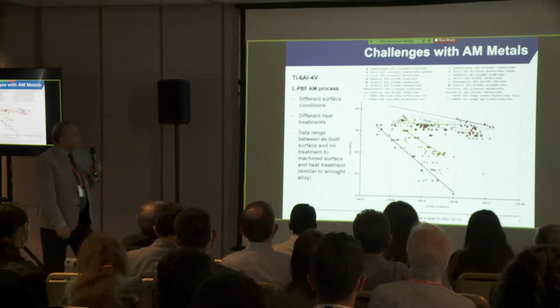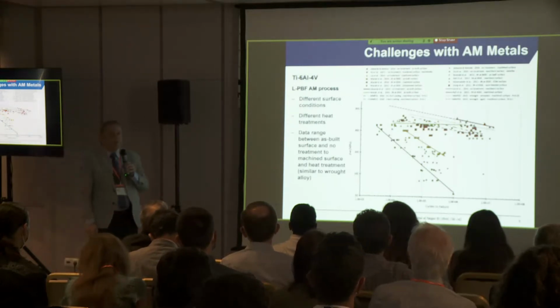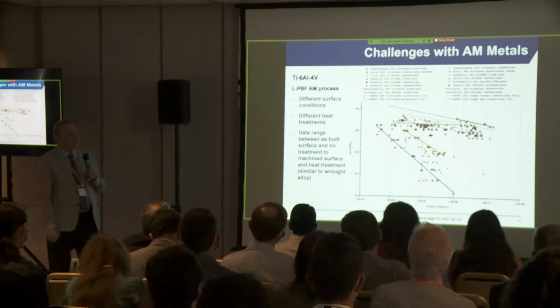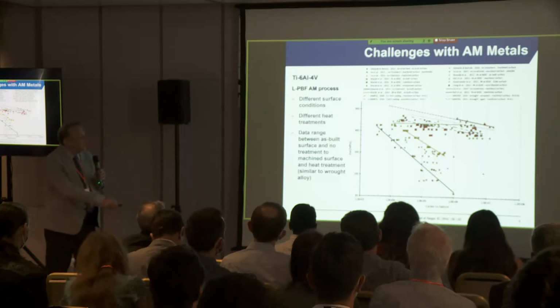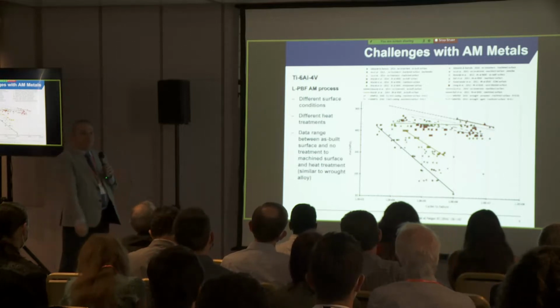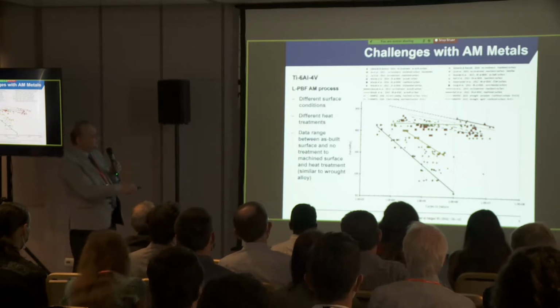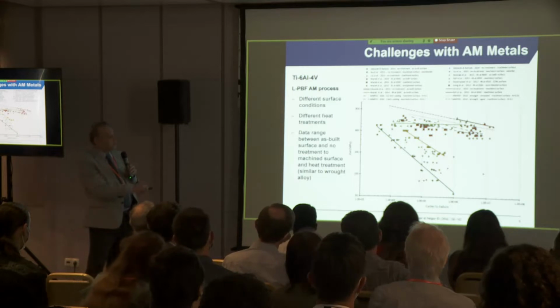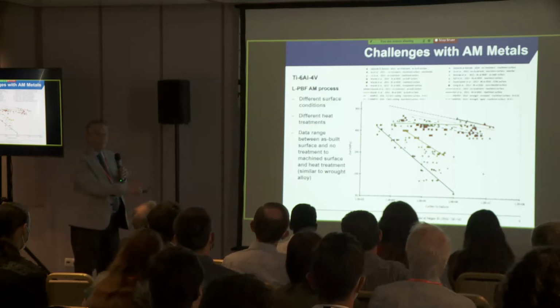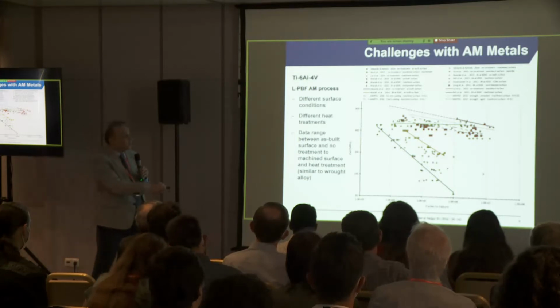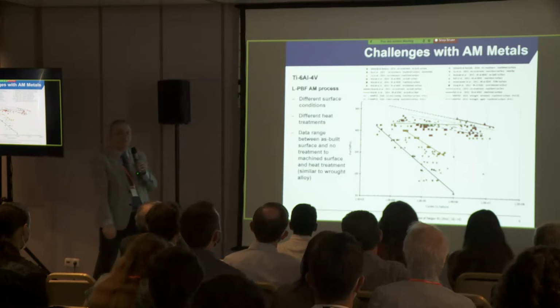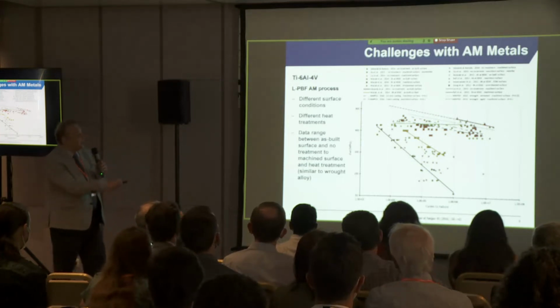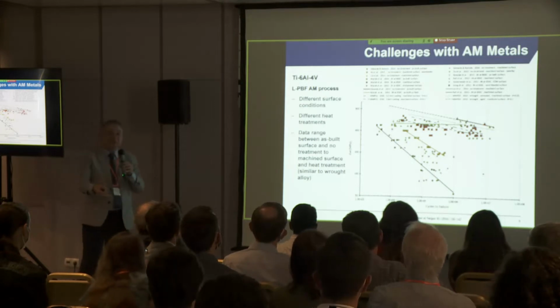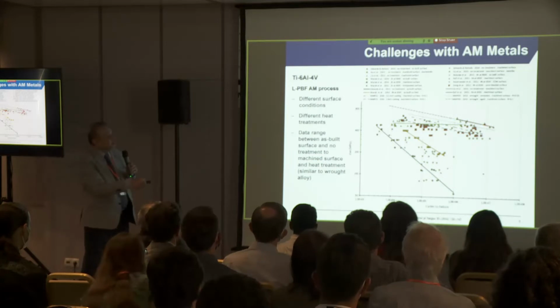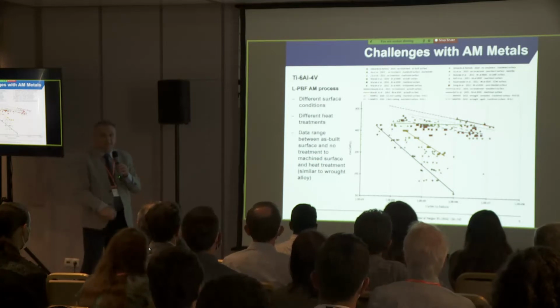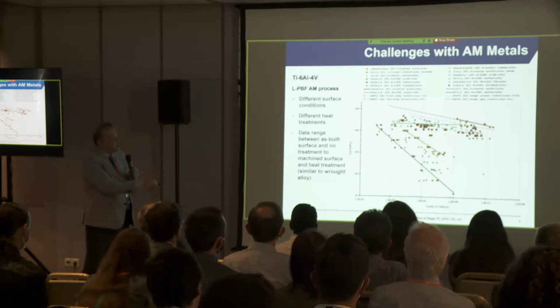Okay, now, because of these variations I talked about, if you look at fatigue performance of just titanium Ti-64, just one single alloy, this is the kind of variation you see in SN diagram, which is tremendous variation of data. So the data could be as bad as what it is here for a process with rough surface finish or as built surface finish and no treatment, all the way up to a process which is machined and not only machined, post-process with HIP, for example, and you can see then the behavior becomes very similar to the wrought metal. Okay, so this is the objective, but there is a long ways going from here to here.